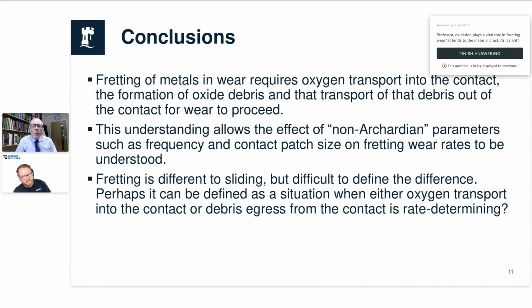When you said it tends to lead to material cracks, if you're asking, does the oxidation in fretting result in cracking of the material, I would say not necessarily. The oxide is formed as the materials fret against each other. It forms because you expose new surfaces. If there's enough oxygen getting in, that metallic surface will oxidize. One thing that I think is still not entirely clear is, does the metal particle come off the surface and then get oxidized, or does the surface get oxidized and then get removed as a metal particle?